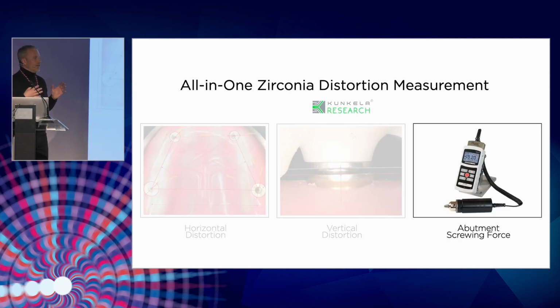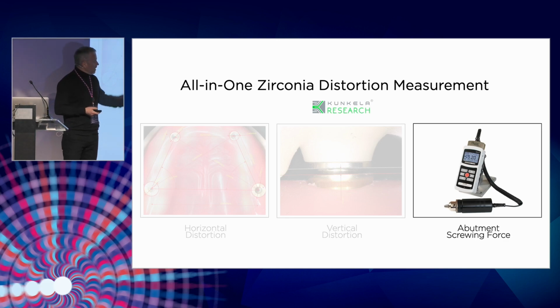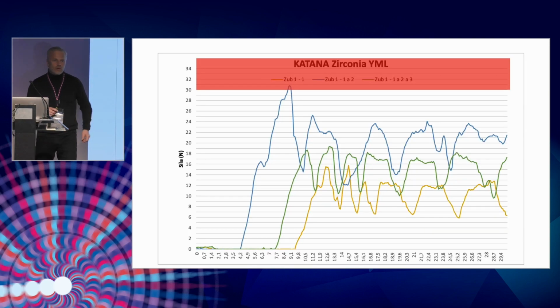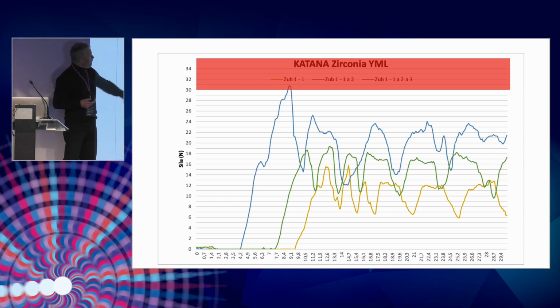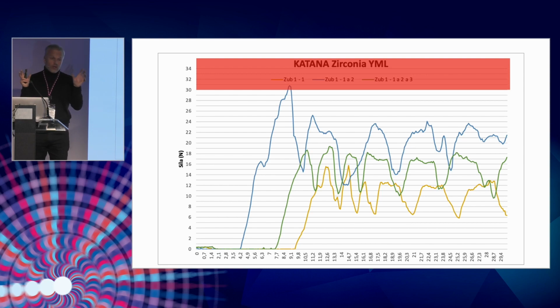And more important for us clinicians is measuring the force which we needed for screwing the frameworks. The recommendation from the company for this kind of screw inside the abutment is maximum 30 Newton centimeters. You can see the biggest force is in Katana zirconia, a little bit over 31 Newton centimeters, which we need for fitting all this zirconia restoration on our sample model.